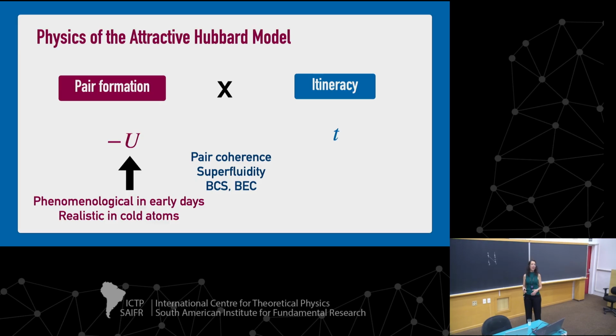The attractive Hubbard model has been studied since the 80s. And in the beginning, what people did is, let's postulate this attractive interaction and just see what happens. And it's kind of phenomenological. In the repulsive Hubbard model, what happens is we have Coulomb interactions, and we disregard longer range interactions, and there is your repulsive on-site interaction. And here we had nothing to say about where this attractive interaction comes from in the attractive Hubbard model, and the answer is, we don't know. And now we know it's from a Feshbach resonance that, the same way we can have the repulsive, we can have it attractive, just tuning into a different magnetic field. So it's a realistic model within the framework of optical lattices.